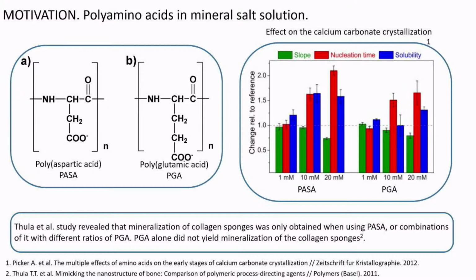different. First of all, it is known from the experiments that glutamic acid does not yield mineralization of collagen sponge as aspartic acid does. And second of all, it's known that there is a different effect on calcium carbonate crystallization, and aspartic acid is more of an inhibitor, if I can say that, for the crystallization process than glutamic acid. So to understand the nature of these experimental results, we performed molecular dynamics simulations.